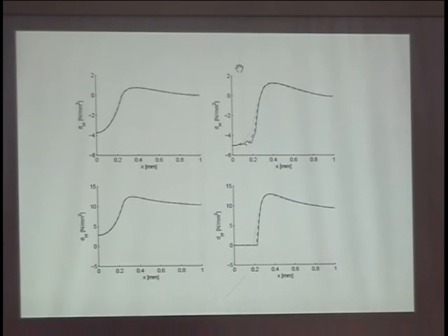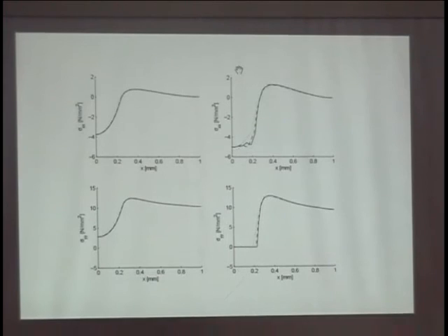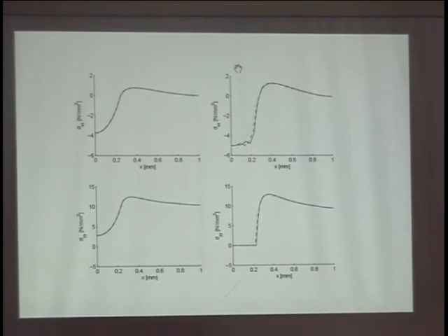So RVE size, representative volume element size, what is that? That's a couple of heterogeneities together. L going to 0 would then mean a material where the inhomogeneity is very small, like glass. So then you would go back to near spike, near singular. So when L is 0, will you get infinity? Yes. Okay. So you see, you can't avoid it.